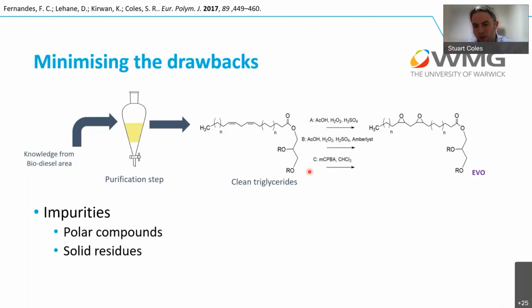This one works a little bit, but in terms of waste and atom efficiency, it's really not very good. So we shied away from the mCPBA long term and actually found a route that utilized a little bit of acetic acid, a little bit of sulfuric acid, a bit of hydrogen peroxide, and the Amberlyst, which is an ion exchange resin. And the mix of this allowed us to do quite nicely controlled epoxidations without ring opening.